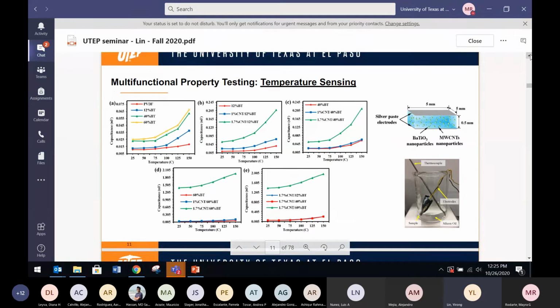We also took it one step further because we know these ceramics have dielectric properties. In other words, they can store electrical energy. So once you measure the capacitance, you can back calculate the temperature. I'll just guide your attention to the picture in the middle top row. You see the green line has 1.7 weight% of carbon nanotubes and 12 weight% of barium titanate. With the increase of temperature on the x-axis, you can see the capacitance also increased. So basically, if you measure the capacitance, you can back calculate the temperature. So you have this embedded sensing for temperature as well. Next slide.